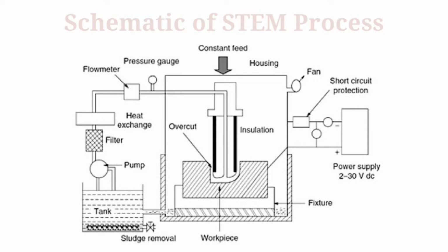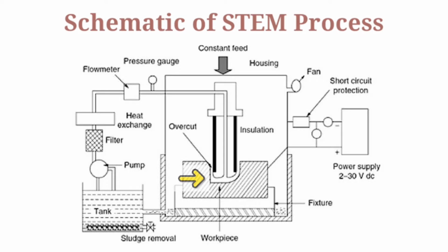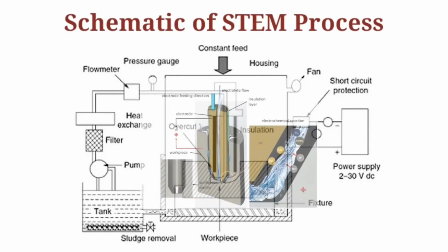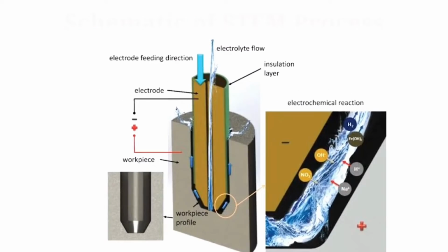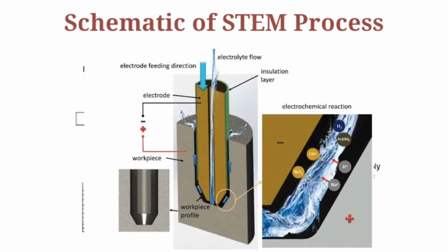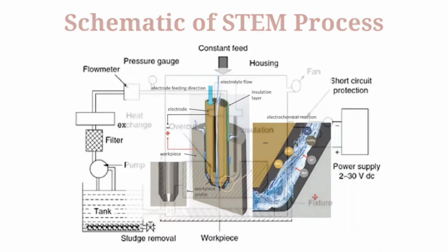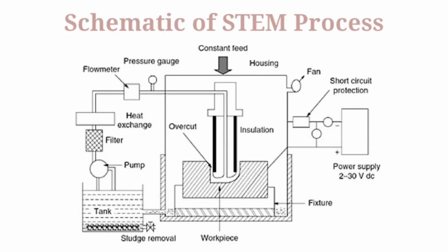A smaller gap at higher voltage causes boiling of the electrolyte, which eventually damages the insulating coating and hence affects the geometrical and dimensional accuracy. The tool is given a constant feed rate to maintain the constant machining gap. The feed rate is about 1.5 mm per minute.